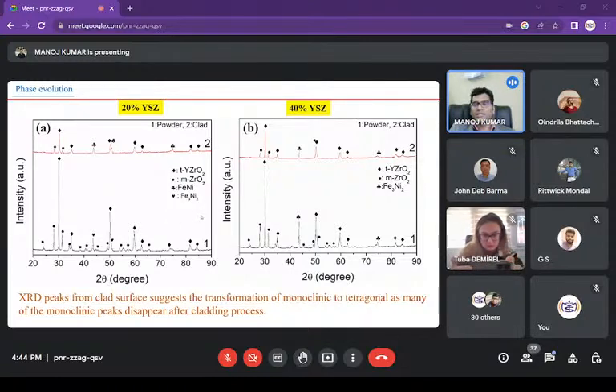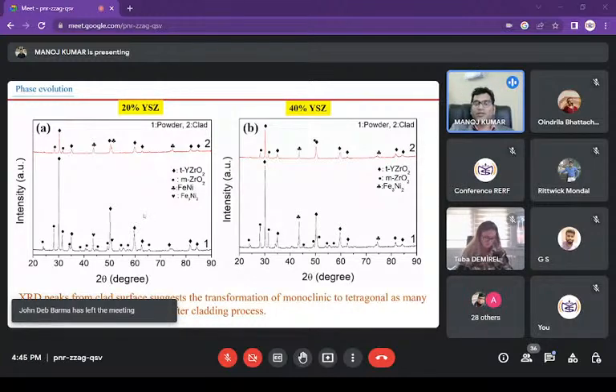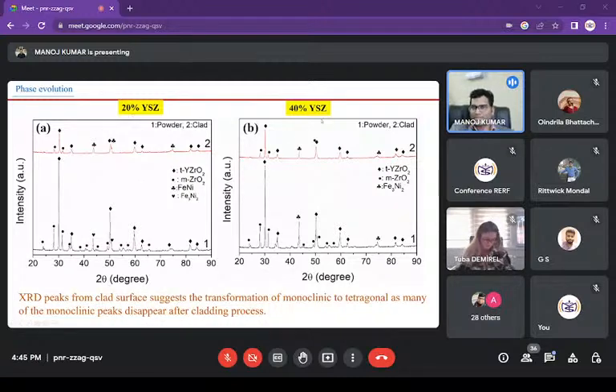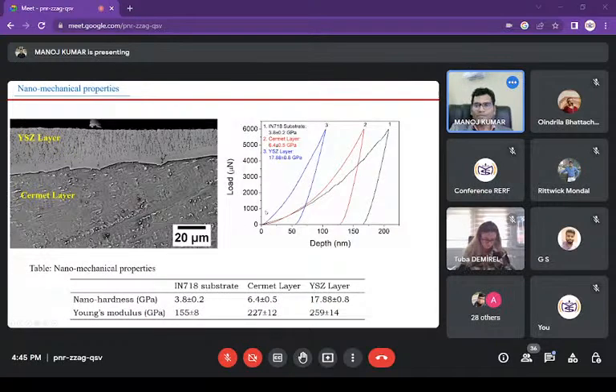So a stable phase is always looked after for better stability of the component. So that is one good thing we achieved, that laser processing also stabilizes the tetragonal phase of YSZ. And this we observed for both the cases where we used 20% of YSZ and 40% of YSZ. Now we try to understand what mechanical properties are affected by this and how they evolve. So of course, the substrate will have lower hardness because it is purely metallic, and when we have a cermet layer, we see an increase in hardness.